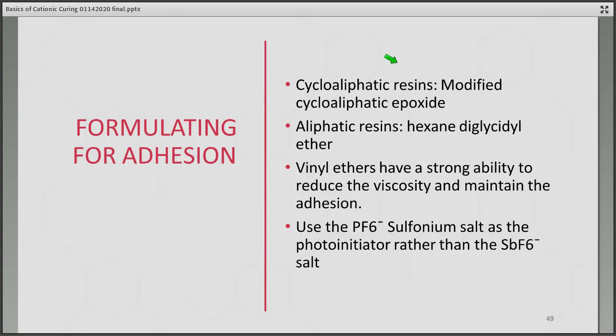Say if you wanted to formulate for adhesion, it could be because it's a difficult or challenging substrate, or you're actually formulating for a cationic adhesive. You can use a modified cycloaliphatic epoxide. Here, you can use an aliphatic resin such as hexanediol diglycidyl ether. It tends to improve the adhesion of your formulation. Vinyl ethers have a real strong ability to reduce the viscosity, as we talked about earlier, but they also maintain the adhesion at the same time. So you may want to add a few percent, 5 to 8%, of a vinyl ether.